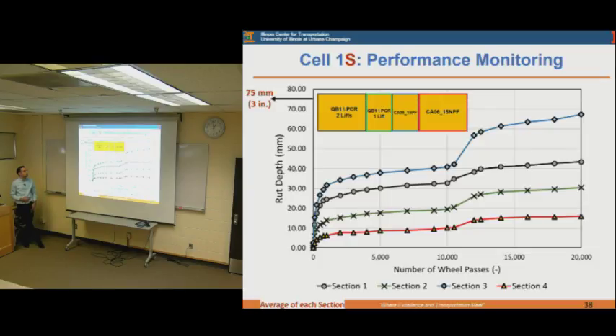Overall, our failure criteria, or the target that we were shooting for, was 75 millimeters or 3 inches of rutting in the construction platforms. And as most of you know, these construction platforms usually don't take up to 20,000 cycles. It's going to be just a few number of cycles. But we wanted to take it to the higher number of cycles and see. Nevertheless, we weren't getting the 3 inches of rutting in any of the test sections overall.